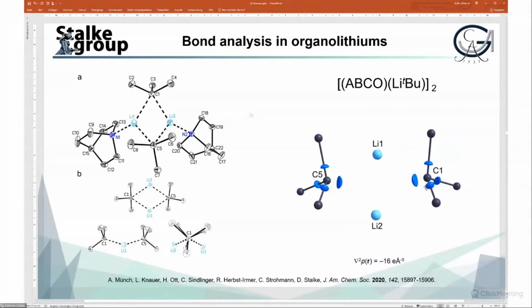If you switch the carbanion from the isopropyl to the tertiary butyl, then we get a dimer. And again, in the dimer, we have a puckered ring, arranged in an eclipsed fashion, where the lithiums, of course, have to contribute to the overall crowding, and then it's quite clear that the ring needs to be puckered.